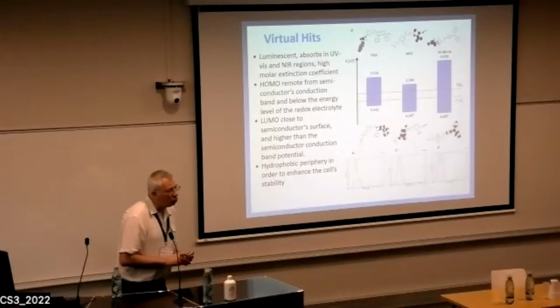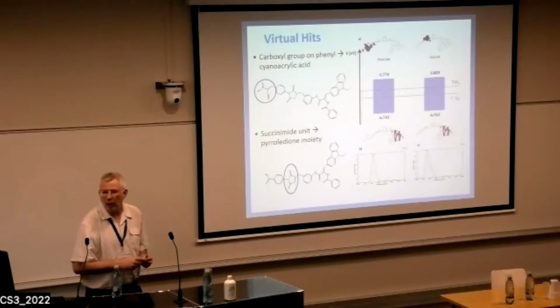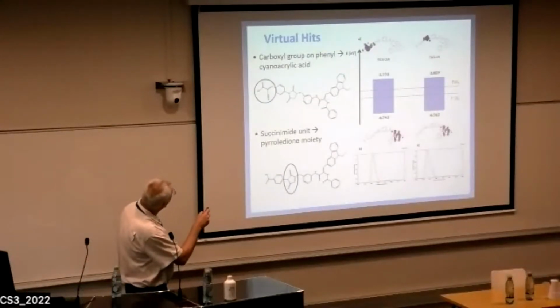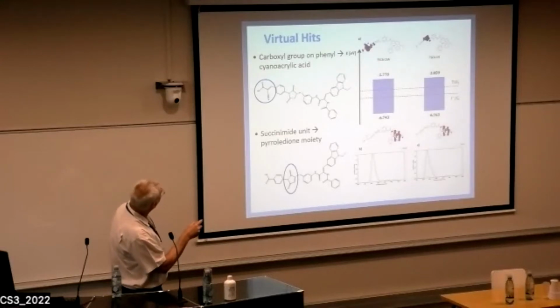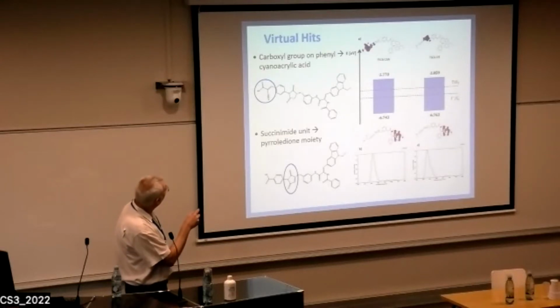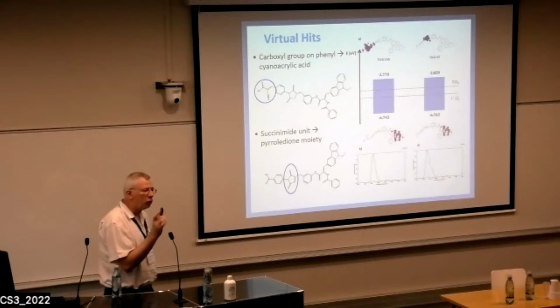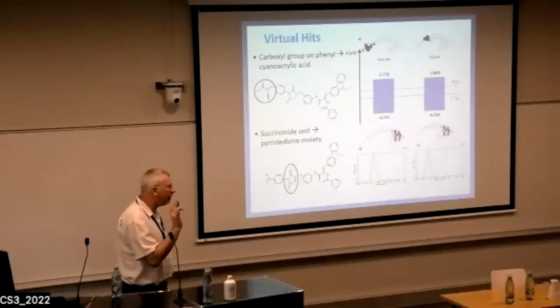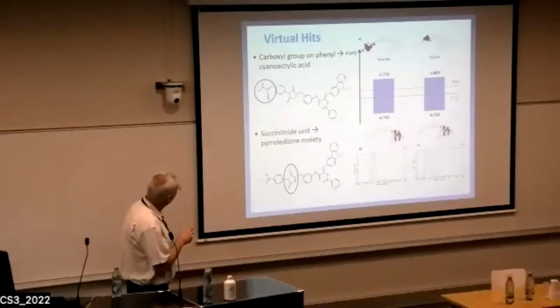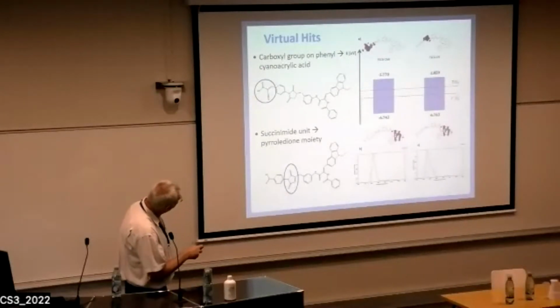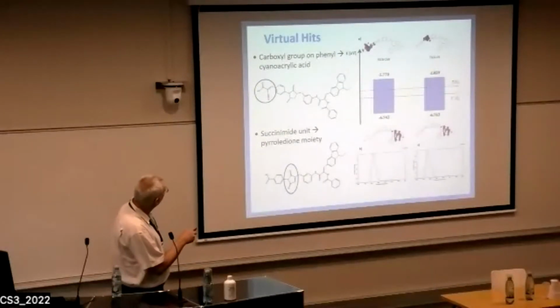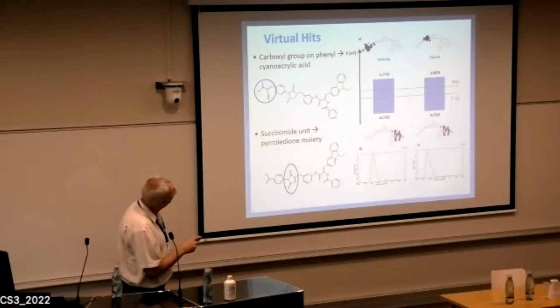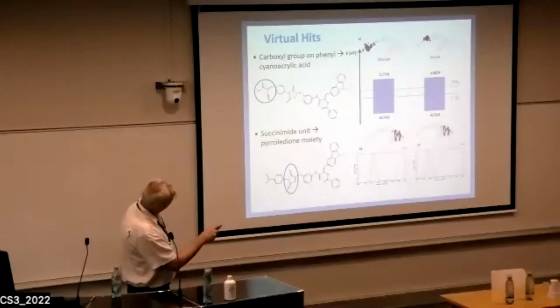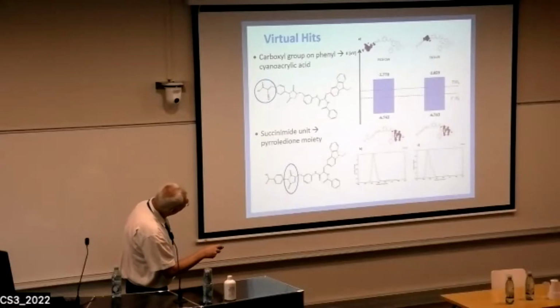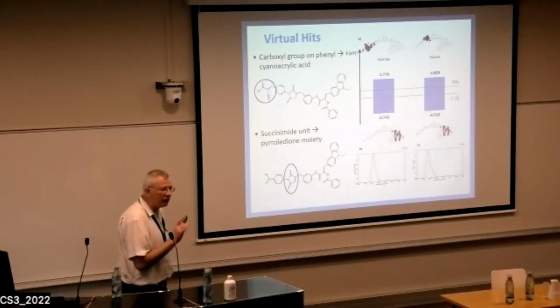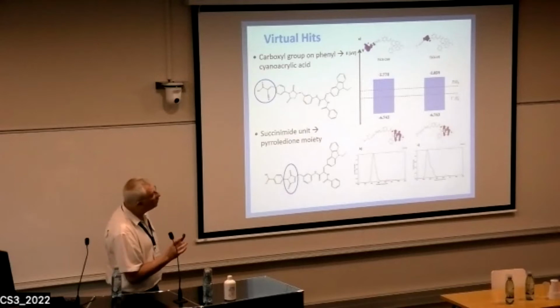So we made two changes to one of the compounds, basically replacing this moiety, which was initially a carboxylic group, by a cyanoacrylic acid, because we saw in other cases that it is a good substituent here, and we changed this moiety, which initially was succinimide, to this one. We repeated the calculation. HOMO, LUMO stayed the same, and we got a small shift to the right, which is exactly what we wanted. So these are the two candidates.